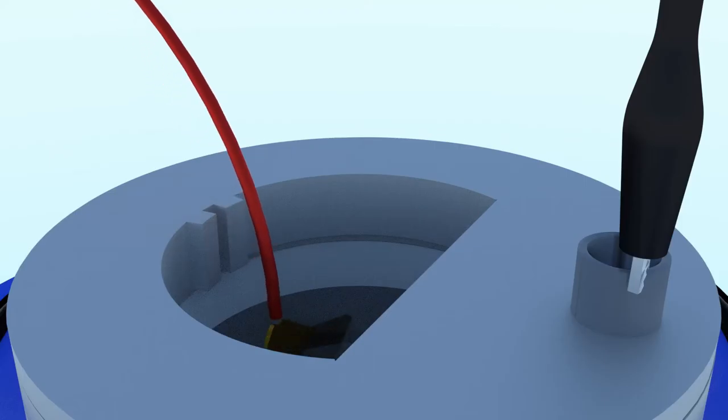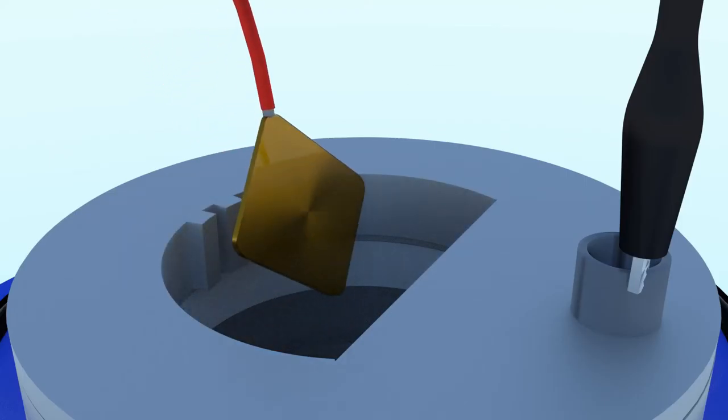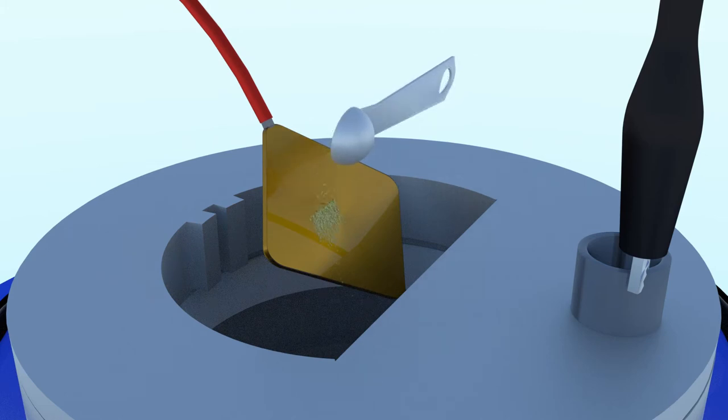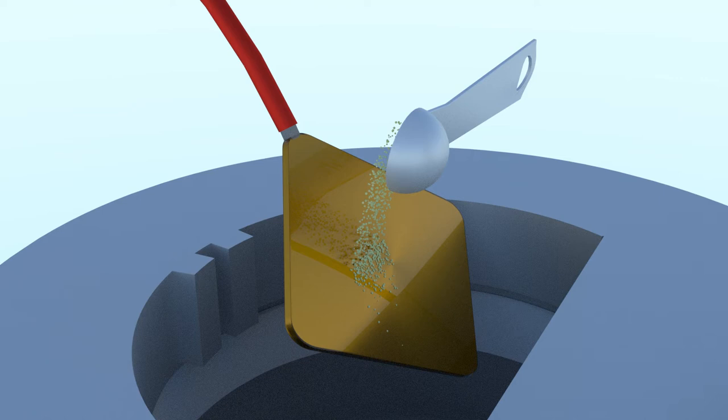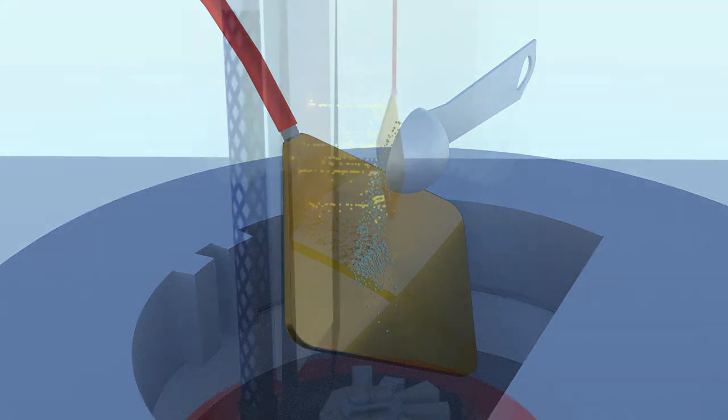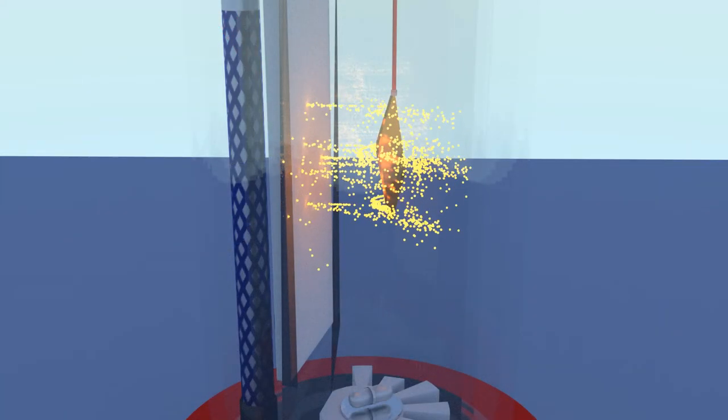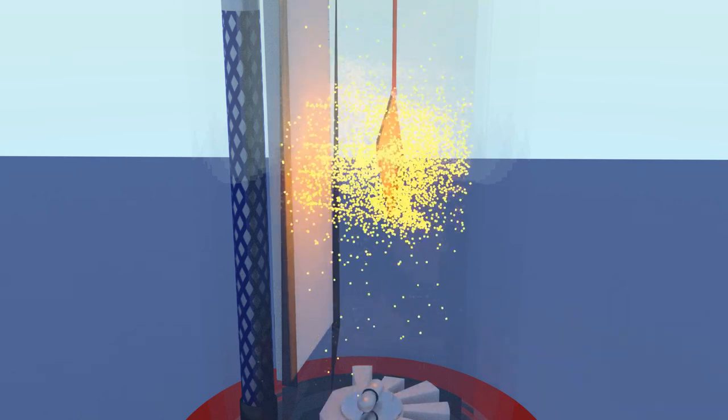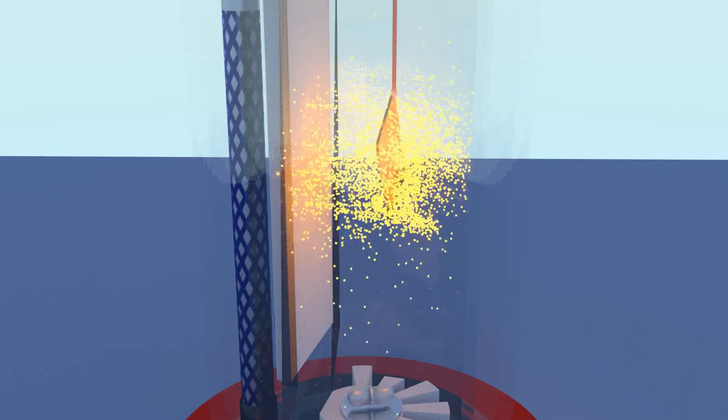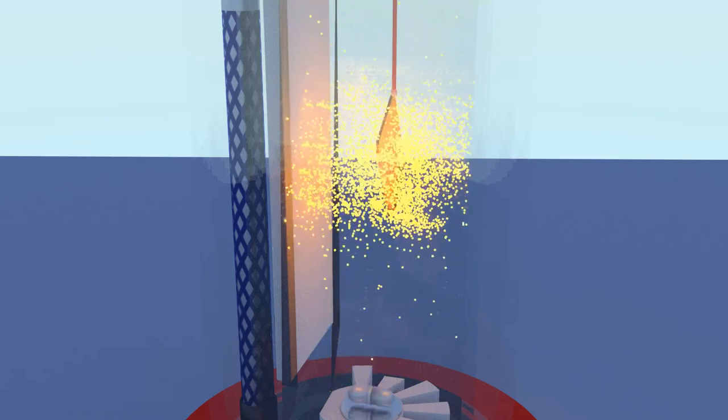Now, lift your gold out of the water. Pour 1 quarter teaspoon of catalyst on the gold, then immerse the gold back into the salt water. The use of catalyst is essential to the dissolving process. Catalyst is like a starter motor for a car. Without catalyst, the base metals in your carat gold - the copper, zinc, and other metals - will dissolve, but the gold content will remain undissolved.